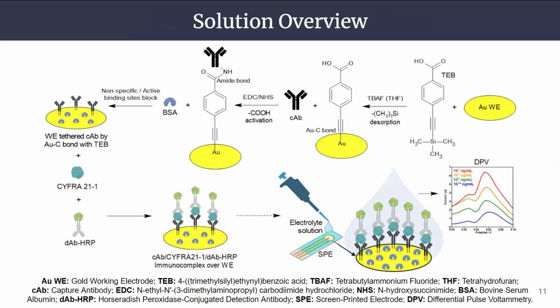So we developed an electrochemical immunosensor using gold nanoparticle screen-printed electrodes and a gold-carbon binding approach for antibody immobilization. The gold-carbon bridge was achieved using TEB by removing the trimethyl group in a reaction catalyzed by TBAF. So the amine groups of the capture antibody attach to the carboxylic groups after their activation by EDC/NHS, creating an amide bond. Then BSA is used to block the remaining active and non-specific binding sites so that CYFRA can be recognized by the capture antibody and the detection antibody, which will generate a signal by differential pulse voltammetry that we can then relate to the protein concentration.